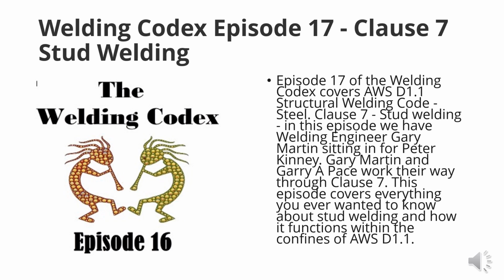Thoughts, Gary? Yeah, it's not quite like sticking a rod, and usually, but not always, there's a little ball of aluminum to act as both an arc initiator and a fluxing agent. The majority of the shielding or protection is served by the ceramic ferrule that is always around the base of a stud. The initiation is, there's a solenoid in the gun. You pull the trigger, it establishes an arc, pulls it back a little bit to a preset amount, and then plunges it in after a timeout.